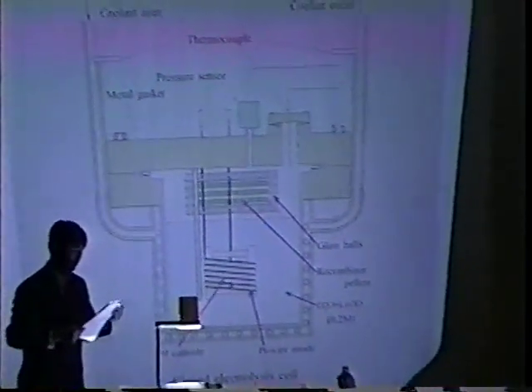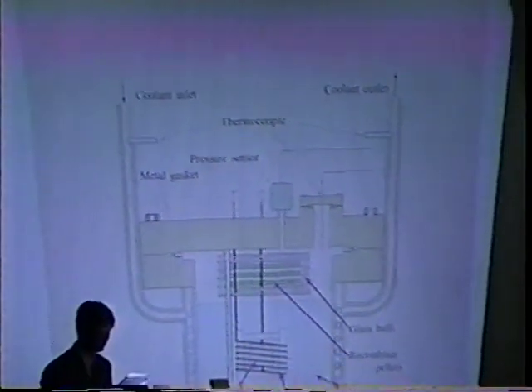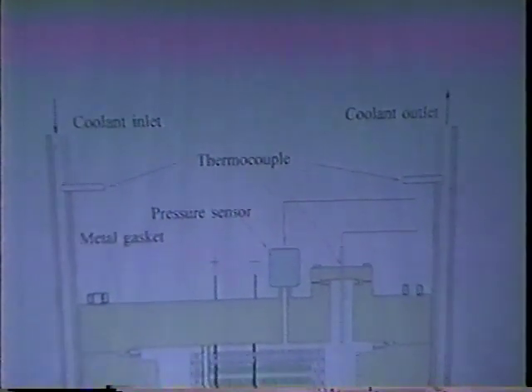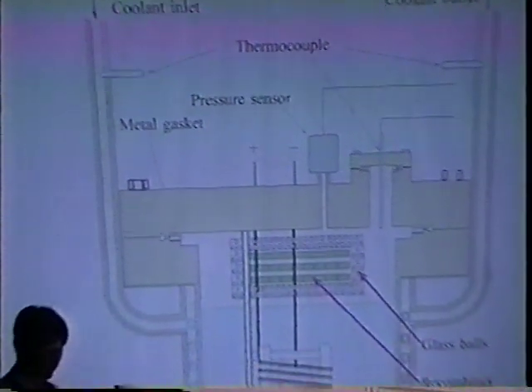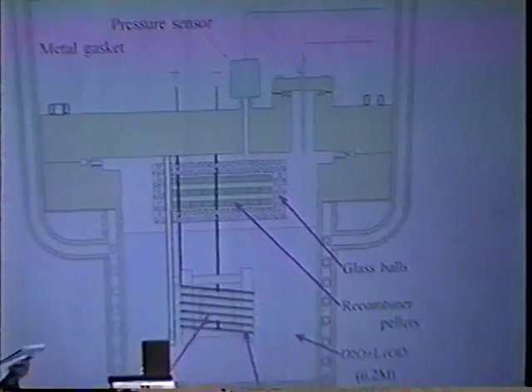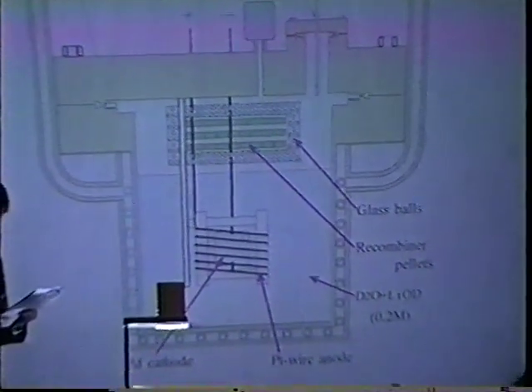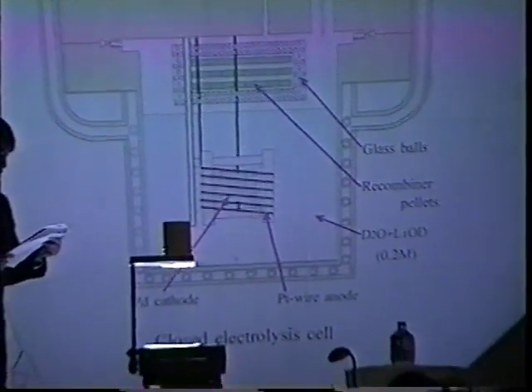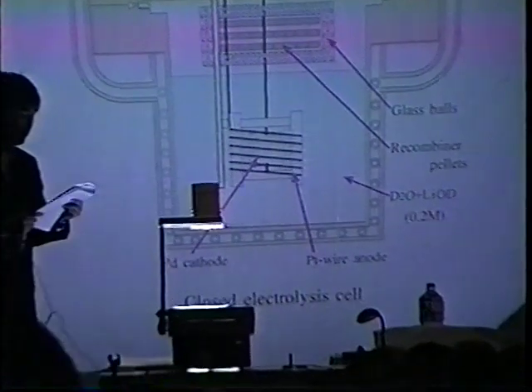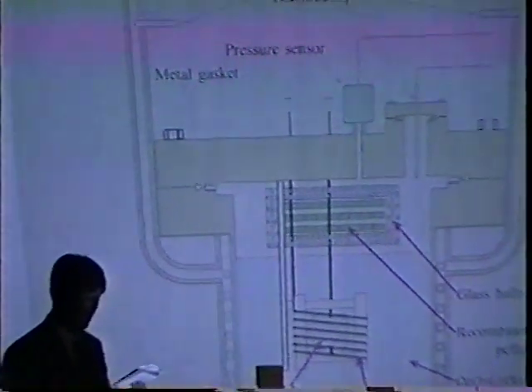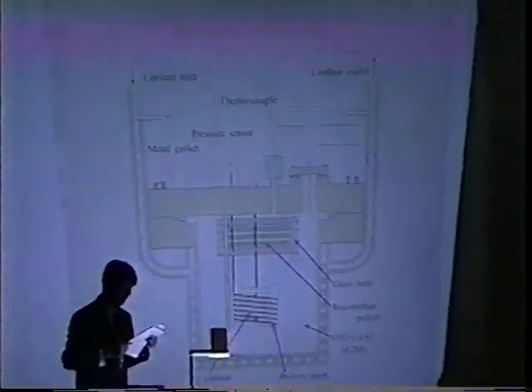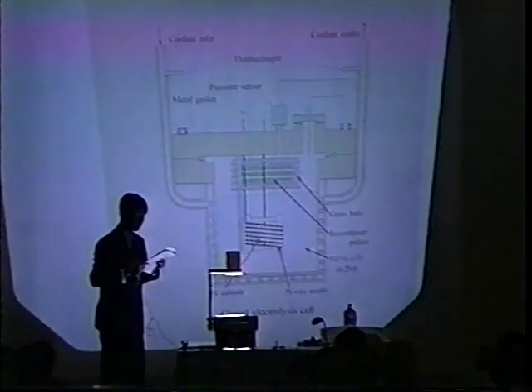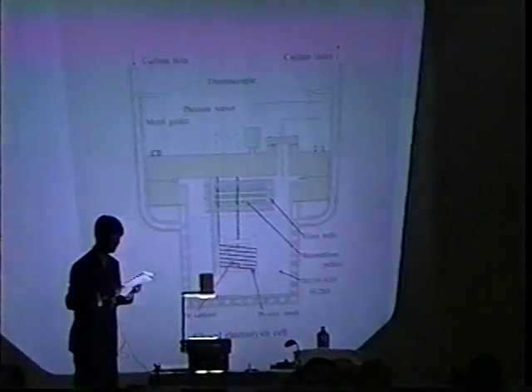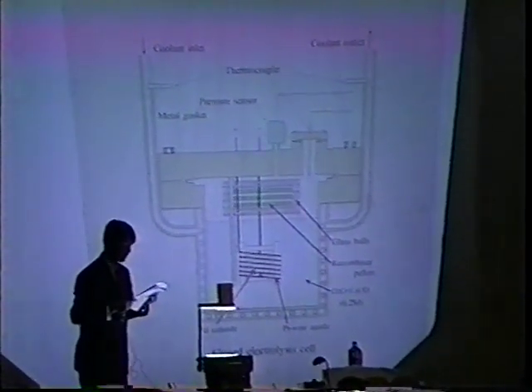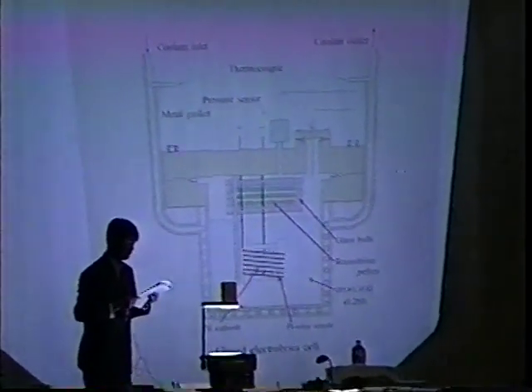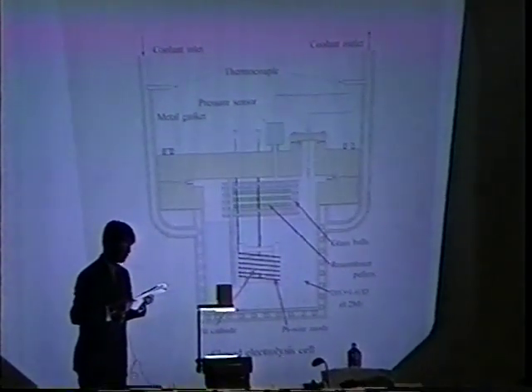This shows a cross-sectional view of the newly designed cell. This cell has a relatively large volume, 738.4 plus or minus 4.1 cc, so that the electrolysis can be carried out with relatively high input power, namely several 10 watts. The cell vessel is made of stainless steel coated with Teflon, and a spiral copper cooling pipe was wound around it. Temperatures at the inlet and outlet points of the cooling water were measured with chromel-alumel thermocouples. Output is calculated from the difference of these temperatures and the flow rate of cooling water.